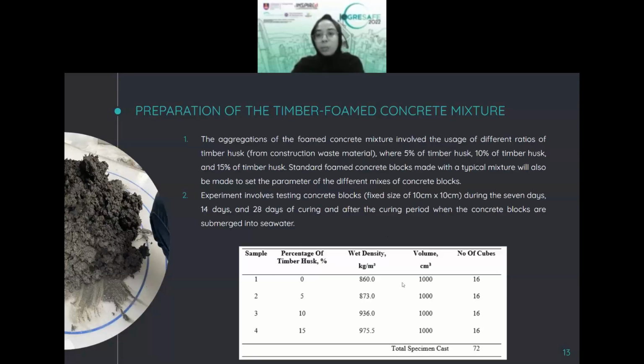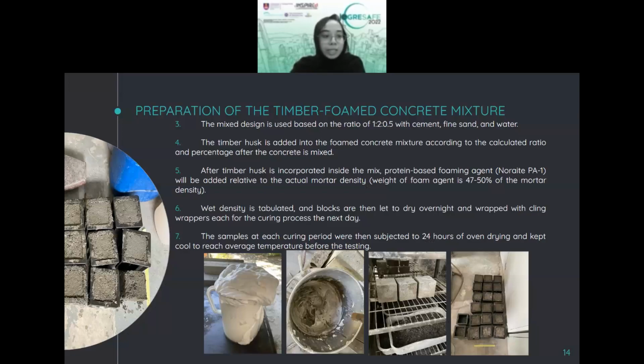So this is the tabulation of the dimension and the number of cubes I've made for the research paper. It comes out with a total of 72 blocks of foam concrete with different percentages of the timber husk additive inside the foam concrete itself for testing. So afterwards, the mixture is designed based on the ratio as mentioned, using cement, fine sand, and also water ratio. And the timber husk is also added afterwards with the foam concrete mixture according to the calculated ratio.